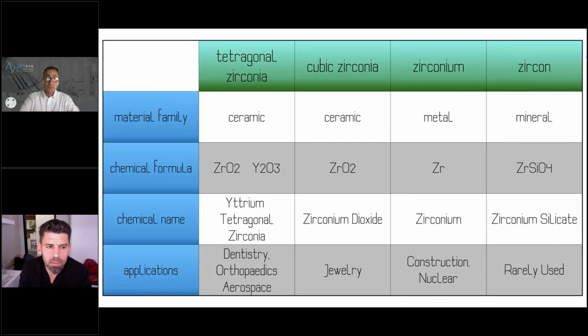And you can see in this chart the different uses for this material. Zircon, as we reviewed, is the raw material. Then we can obtain zirconium, the metal, which is used in construction and nuclear. And then from there, we can transform that into, the first thing is cubic zirconia, and we can see that in jewelry. And then one further transformation will be the tetragonal zirconia, which is zirconia mixed with either yttria or alumina. And this has the dental applications in orthopedics and also in aerospace. And it's used in the aerospace industry because it's a very light material, but a very resistant material. And so the aerospace industry also benefits from this material.